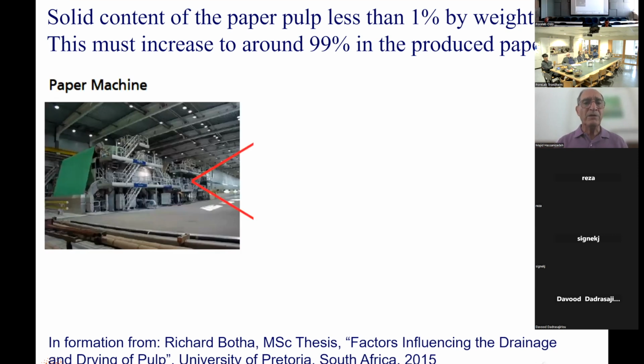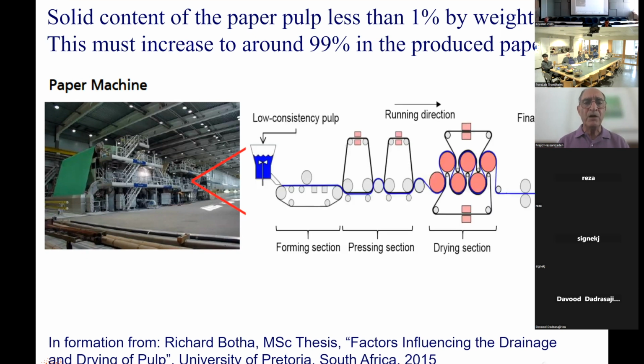And this is done in a paper factory, paper machine, and there are 5 main parts to a paper machine. There is where you make the pulp. Now, low consistency means it's very, very little solid. And then this pulp is taken to a forming section where as much water as possible is removed from it by gravity drainage and by vacuum. So that is done in the forming section.